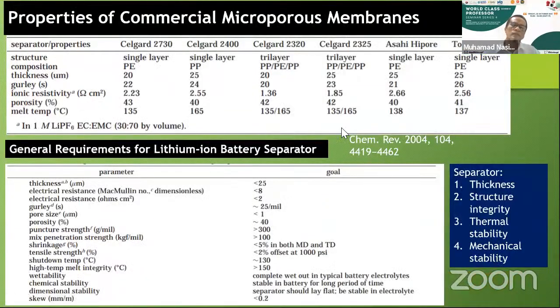This is the basic property of the commercial separator. Most of the material is polyethylene and polypropylene, and the thickness is very important, and also the permeability or Gurley, the ionic resistivity, and porosity. And one important property is the melt temperature of the polymer material.